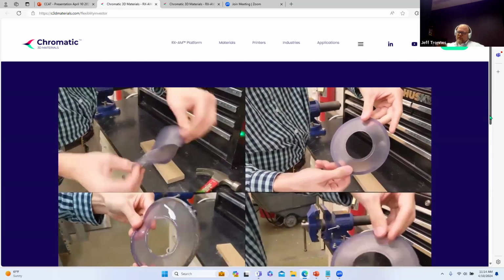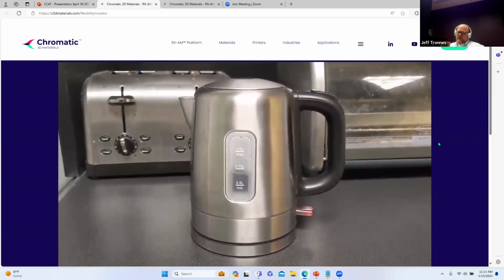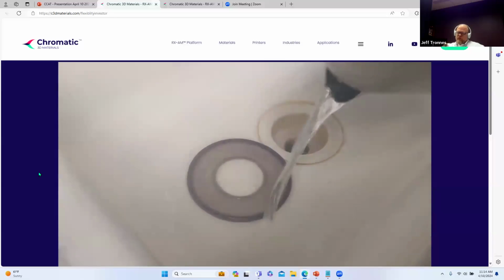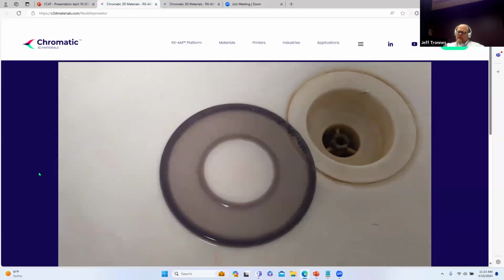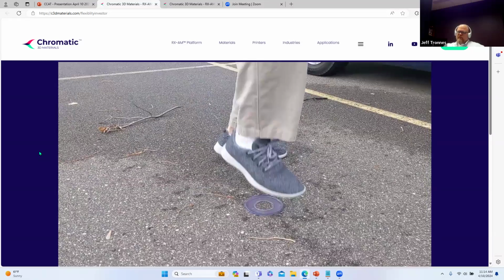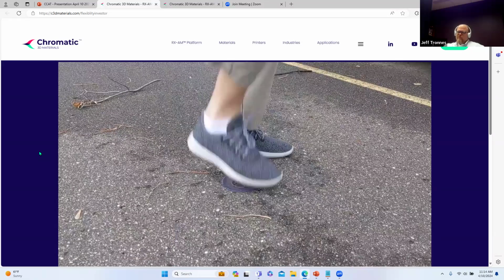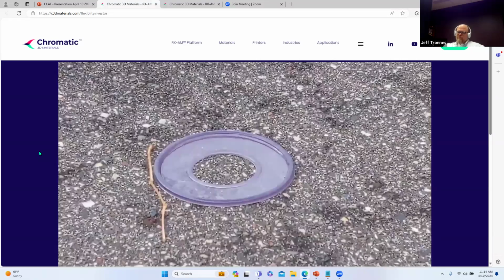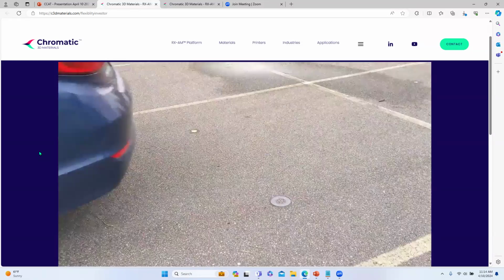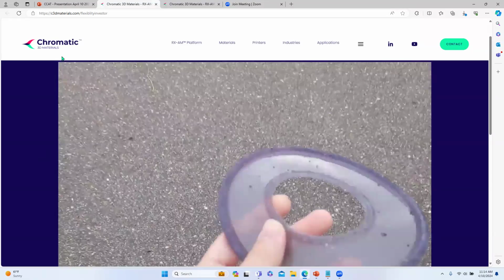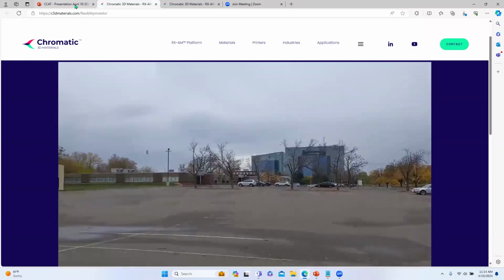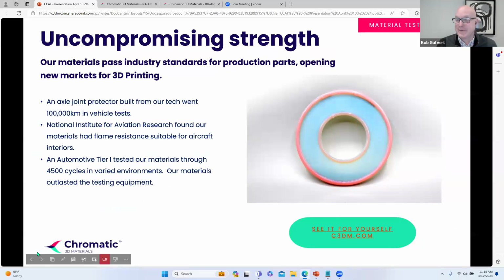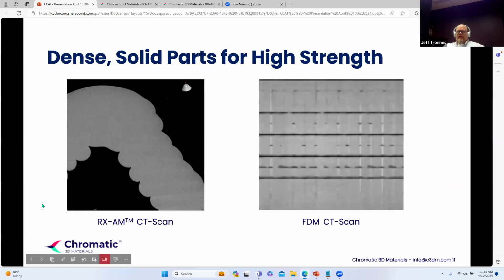What you'll see here is that the thin layer that you can see through is really one layer thick. And then there's a bead on the inside and outside of that to make the seal. And that was that quick.